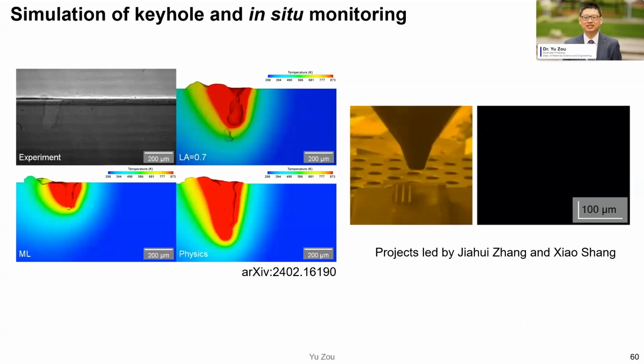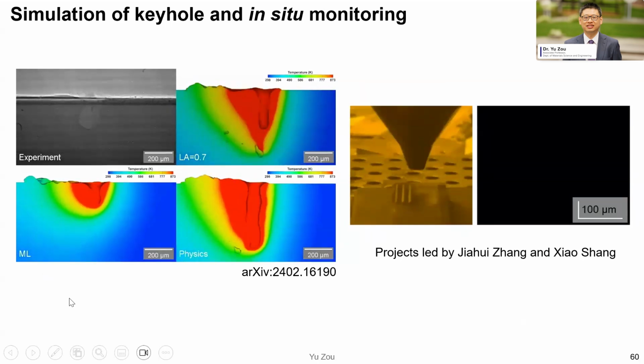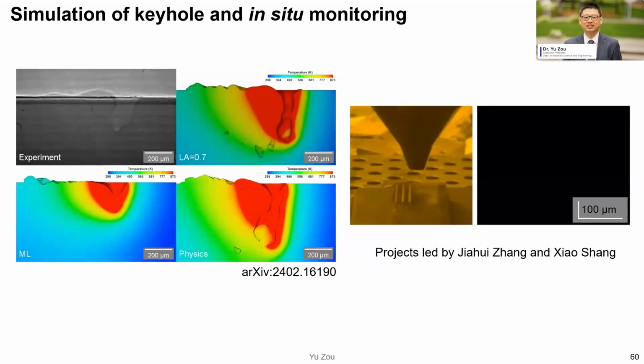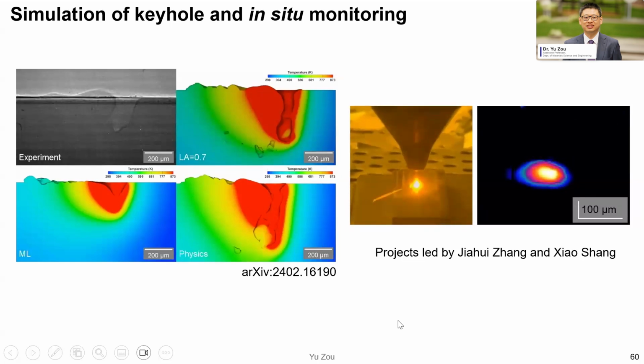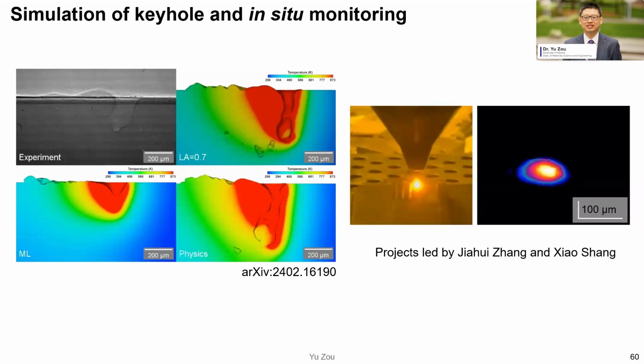Meanwhile, we're collaborating with a few labs to identify the defects during the printing process. For example, we use an AI aided simulation method to predict the keyhole depth. And also we work on in situ monitoring. This is an in situ IR camera, so we can identify the temperature distribution during the printing process.